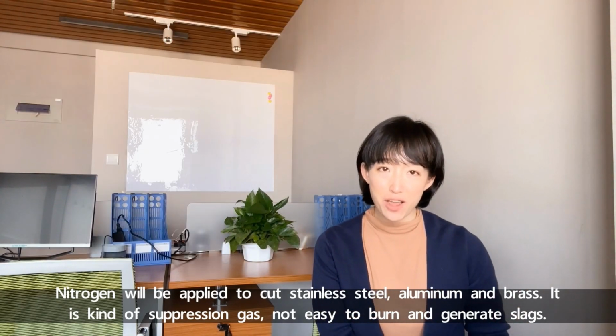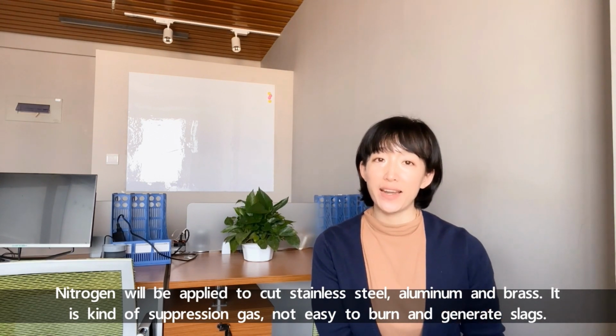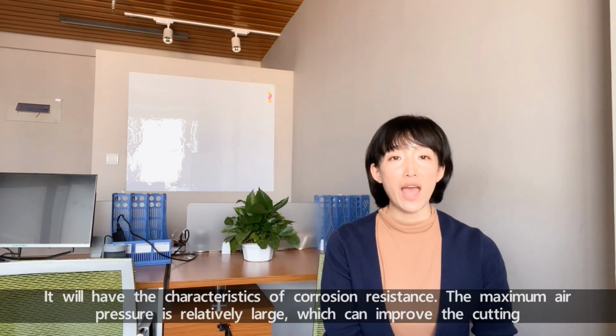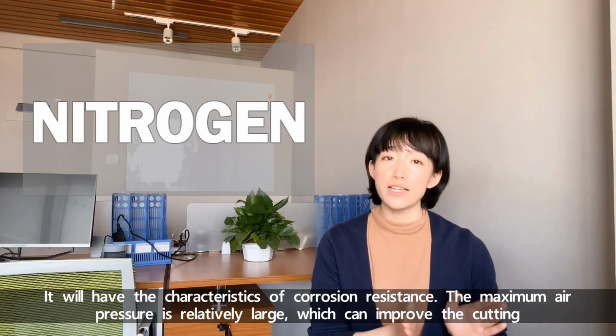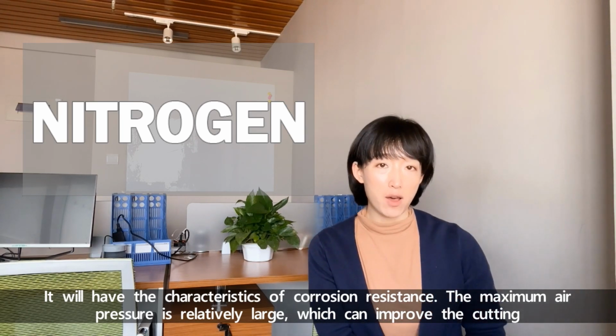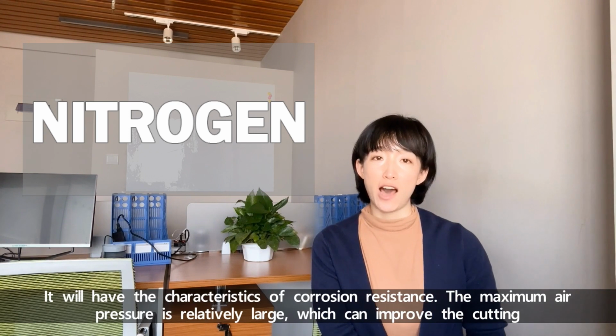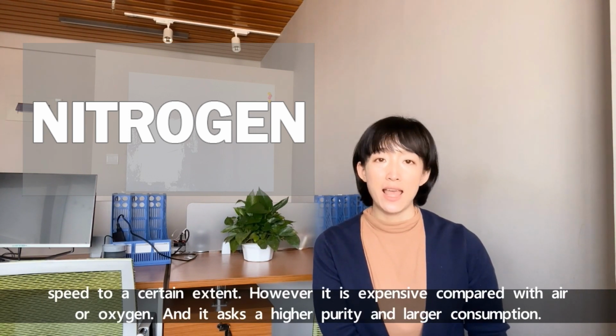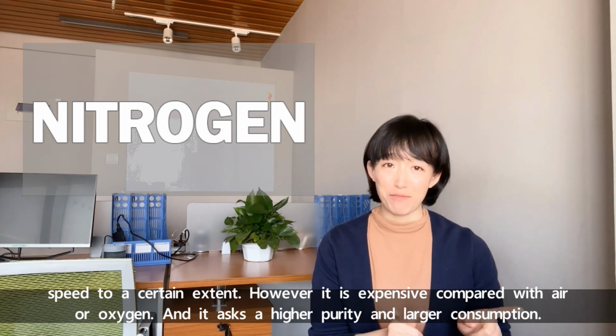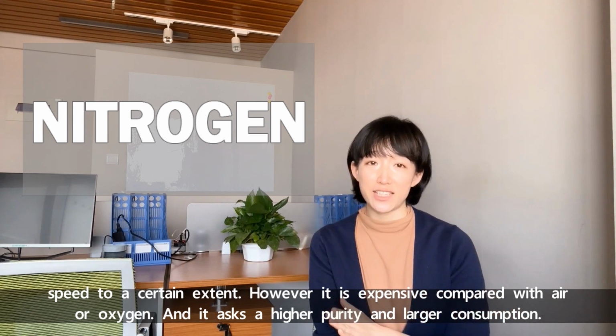Nitrogen will be applied to cut stainless steel, aluminum, and brass. It's a kind of suppression gas, not easy to burn and generate slags. It will have the characteristic of corrosion resistance. The maximum air pressure is relatively large, which can improve the cutting speed to a certain extent. However, it's expensive compared with air and oxygen, and it asks for higher purity and larger consumption.